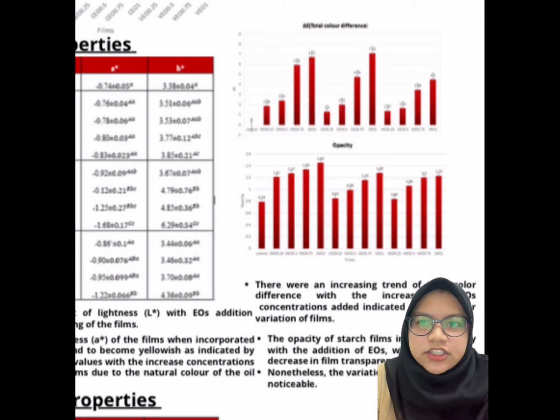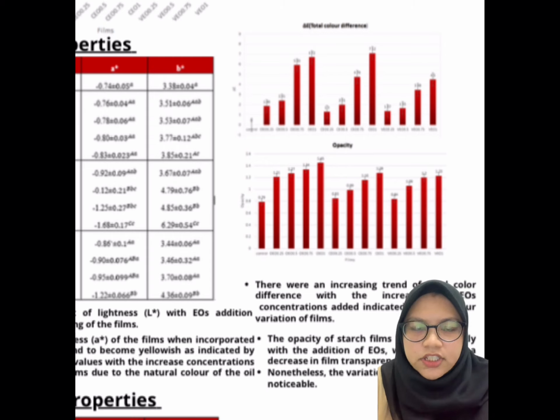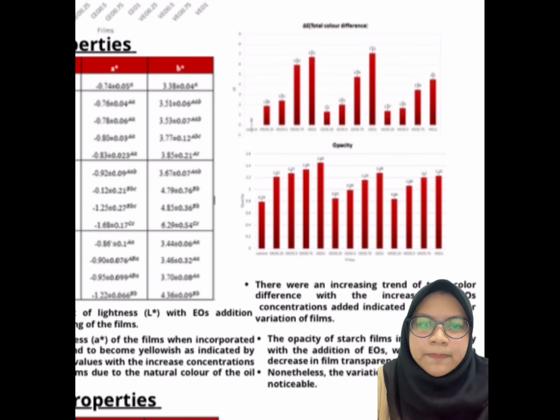Here in the graph, we can see that there was an increasing trend of the total color difference with the increased concentration of essential oil added, indicating a slight color variation of the films. Also, the opacity of the starch film increased slightly, as you can see in the next graph, with the addition of essential oil indicating a decrease in film transparency. Nonetheless, the variation was small and not noticeable.